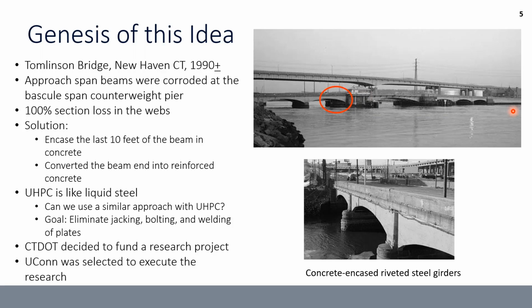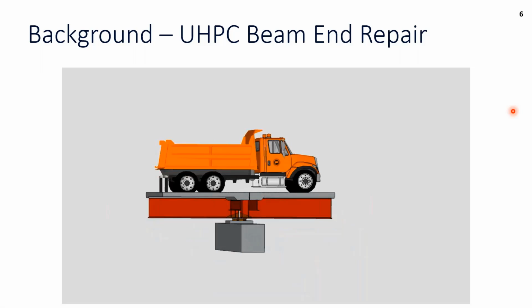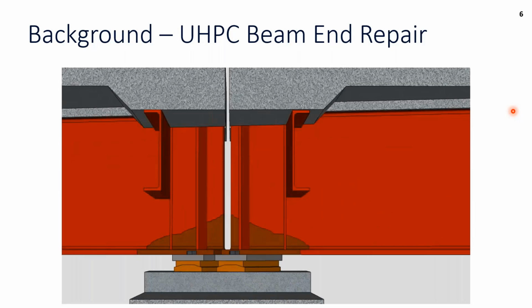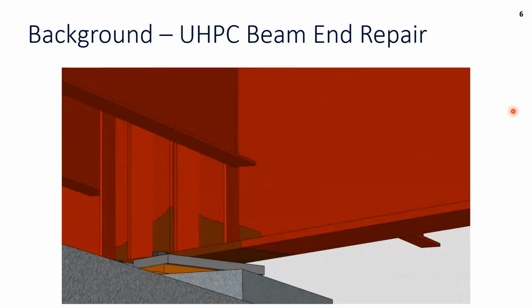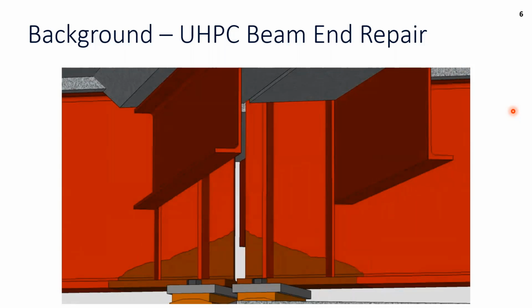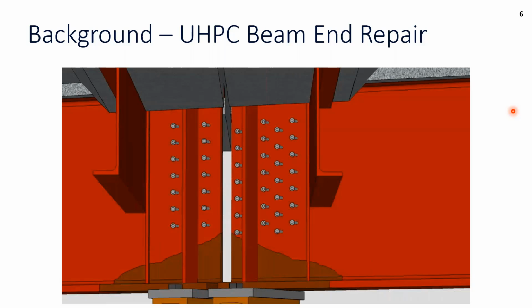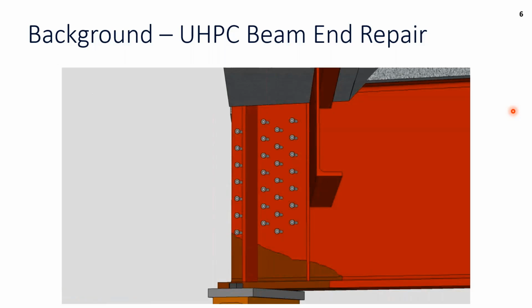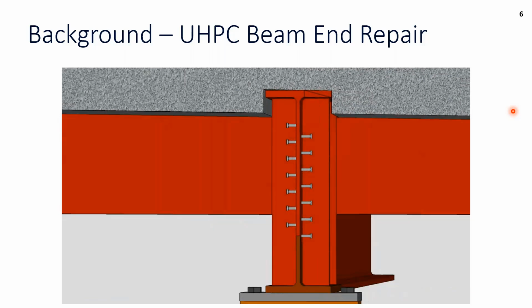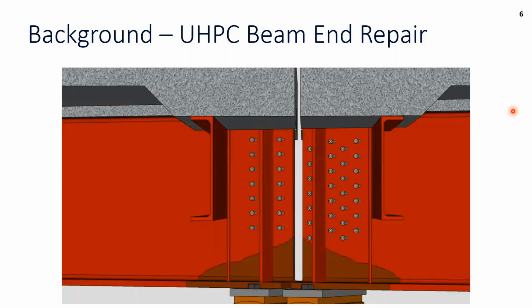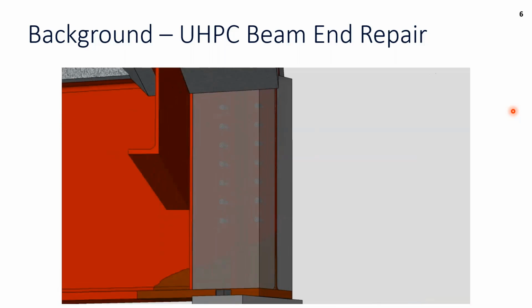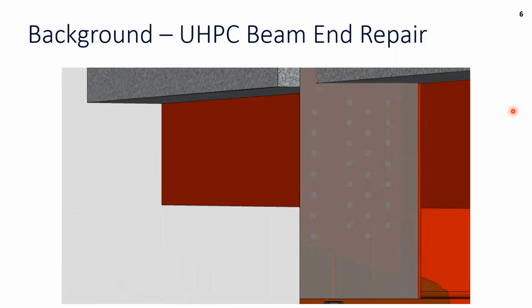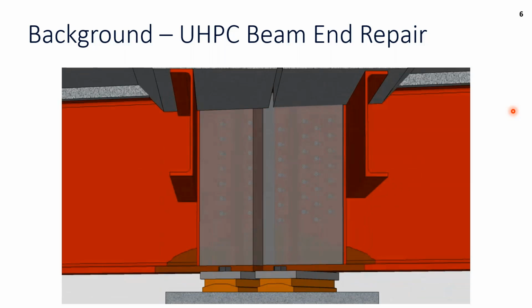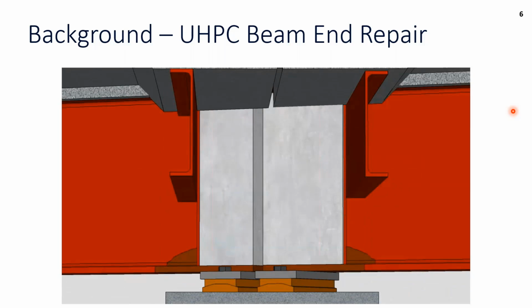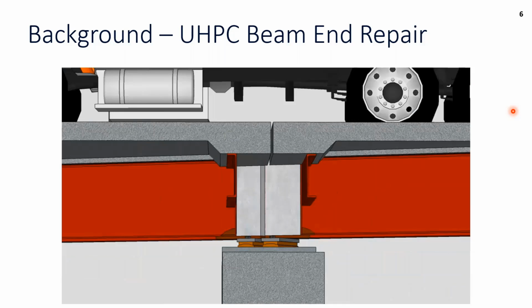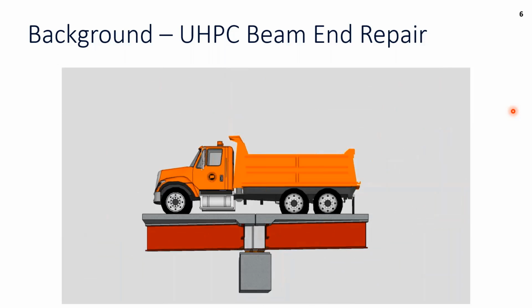Great, thank you so much. So let's kick it off with first understanding what this repair looks like. We can see a beam end with that darker corrosion that reminds you of one of the earlier slides. The first step is to weld headed shear studs to the intact portion of the beam. So we want to clean the surface, weld these with just a stud gun, and then we can encase that full region in ultra high performance concrete. And what this does is create an alternate load path through the studs in the UHPC for bearing forces that bypasses that corroded region at the bottom.